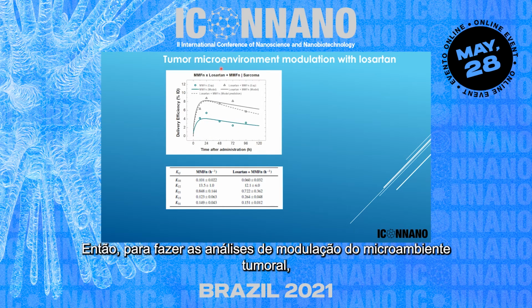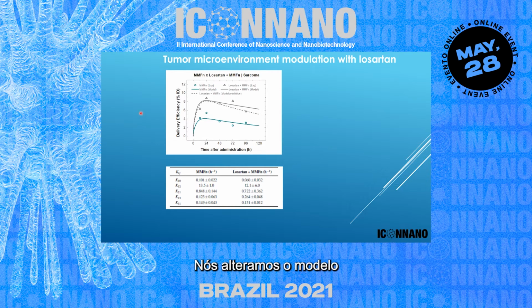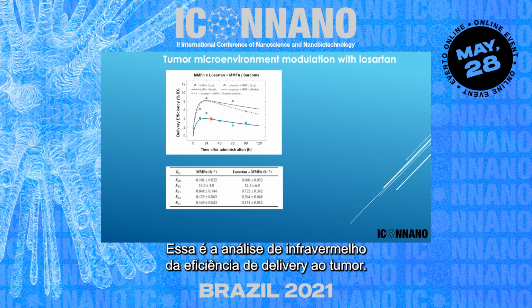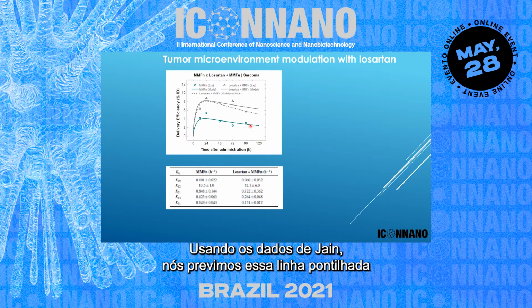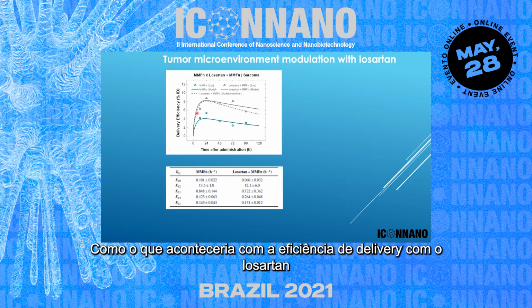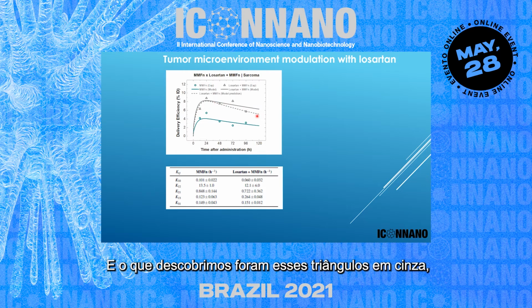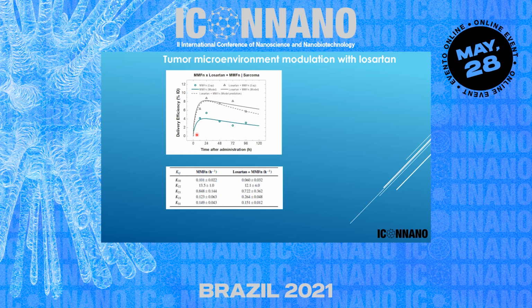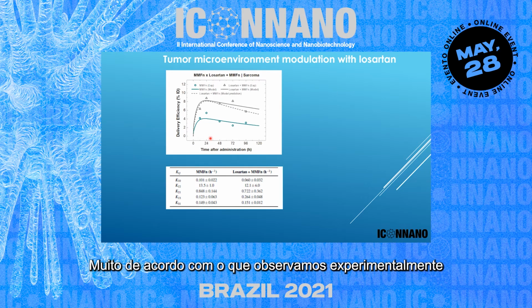So to perform the analysis of tumor microenvironment modulation, we changed the model. We use S180 with losartan. The symbols here are the experimental data. This one here is the sample without losartan, and this is our theoretical analysis of the tumor delivery efficiency. By using the analysis of Jain, we predicted, in the dashed line, what would happen with the delivery efficiency with losartan. And what we found out was the triangle symbols that you are seeing here, which is in good agreement with what we observed experimentally.